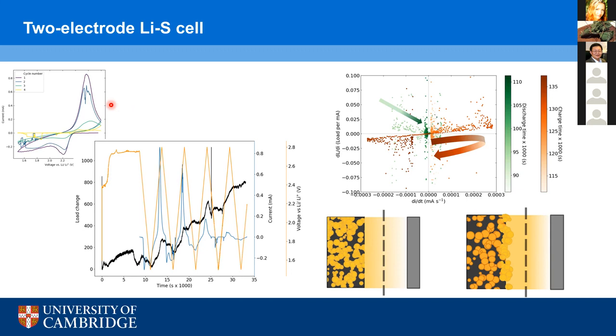So it's tempting at first to attribute the failure of the cell and the poor performance to the formation of lithium dendrites. But the increase in pressure that we saw from the pressure sensor forced me to think about it slightly differently. I think it's quite likely that the decrease in cell current with time and the corresponding increase in pressure was actually due to the deposition of lithium polysulfides at the interface of the cathode and the electrolyte, leading to an increase in cell resistance with time and a decrease in active material utilization, which would also cause an increase in the viscosity of the electrolyte and correspondingly more resistance in the cell and capacity degradation. So it was interesting to see a different perspective on what could be causing the cell failure that I maybe wouldn't have considered normally, that came from looking at the pressure data.